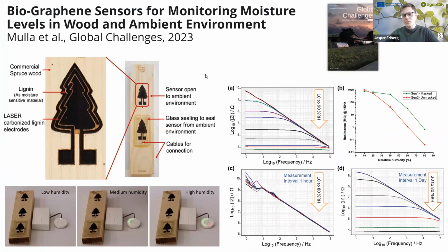So we use this laser graphitization technique and directly made these humidity sensors, which is manufactured directly on the wood. So the carbon itself comes from wood, the sensing element is made from wood, and it's made on wood to measure properties of wood. So it's wood, all about wood here. What we could see was that we can both measure the surrounding air moisture, and we can also track the spreading of moisture inside of the wood, and we can separate the two properties.